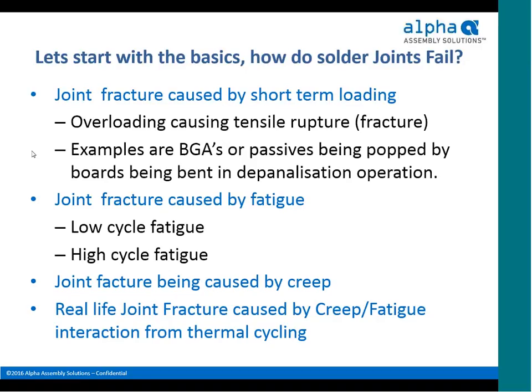A great example of this are large BGAs or passive devices that go onto a depaneling operation in the factory, and while they're being cut out of the panel, they're bent and flexed, and now you've exceeded the strength of the solder joint and you get fractures. That's not the only kind of failure that can occur. These are typically not field-type failures.